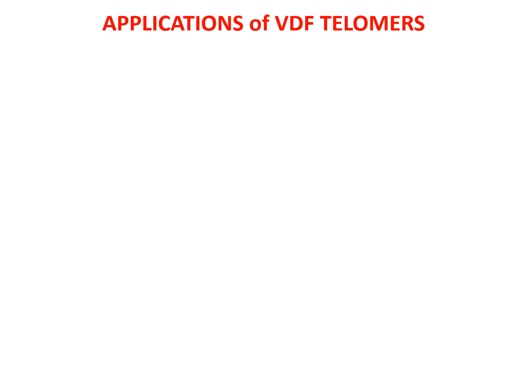What we have done in the lab has been first to investigate some telomers of VDF. This reaction of telomerization has been developed for more than 40 years in the lab. And let's say in the last 25 years, we have done a lot of work on telomerization of fluorinated monomers. For instance, when you use a chain transfer agent of C6F13I, you can do, of course, some controlled radical polymerization by iodine transfer polymerization, but also you are going to stop the reaction when you want in order to prepare some well-designed fluorinated polymers. And these applications are numerous.